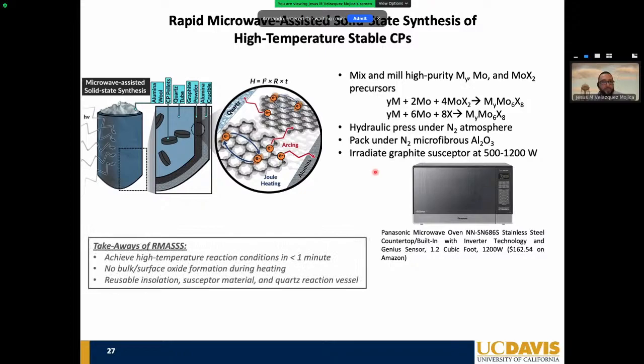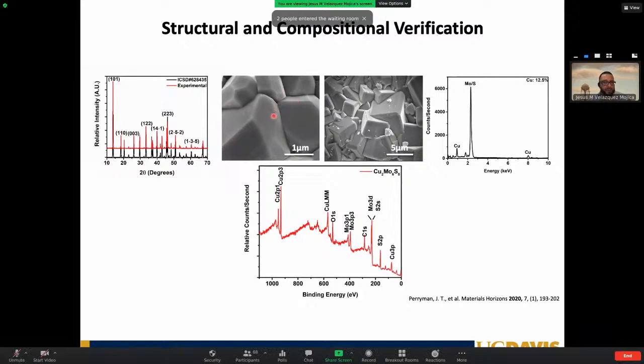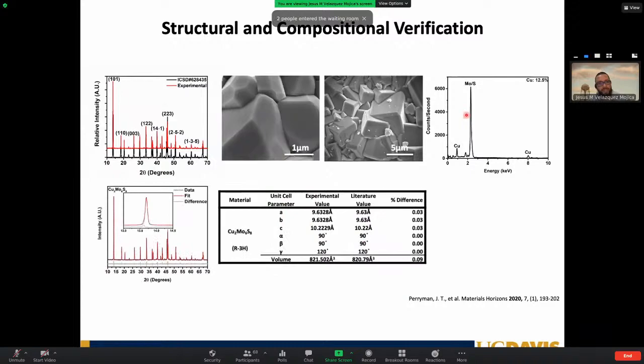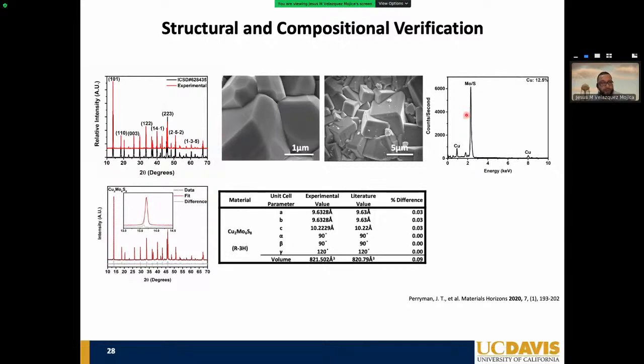Obviously, it has been retrofitted so that you can have an inert atmosphere in there. And there are some synthetic details that one has to carry out, but it works really well. More importantly, it allows us to get high purity material, as you can see here from the X-ray diffraction, beautiful faceted polycrystalline material. We have obviously done our homework and confirmed the bulk composition and the surface composition using EDX and XPS, and done the refinement to make sure that our unit cell parameters match very well with literature.